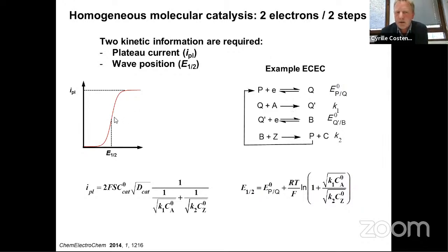And actually, you can get 2 kinetic information, because on the CV, let's assume that you have an excess of substrate so that you reach a plateau. You have on this S-shaped CV 2 kinetic information. One is the plateau current, the one that we have used previously, but you have also another kinetic information, which is the half-wave potential, which is, in other words, the position of the wave. And as you can see from the analytical expression of the plateau current and the half-wave potential, they both depend on the 2 chemical steps here.